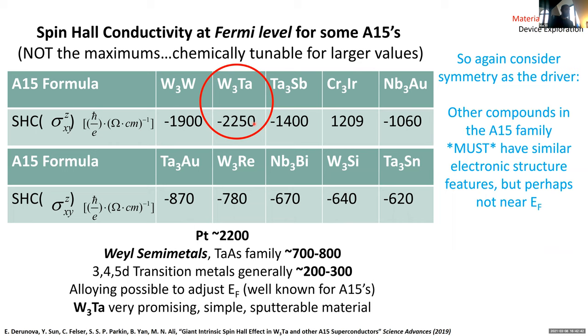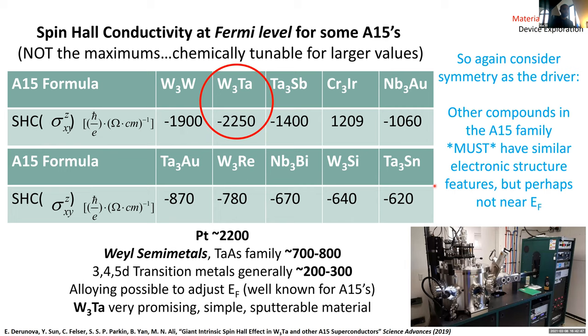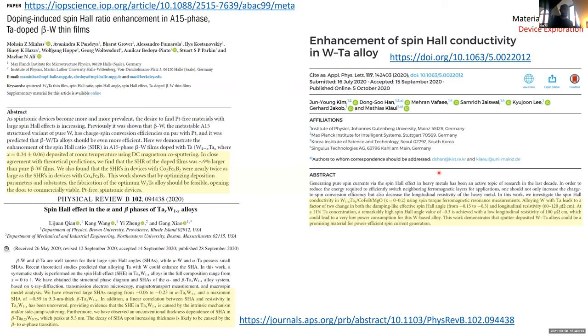So this is one of my other babies, my main piece of equipment. This is my sputtering machine that I have here in Halle. And so we, as well as several other groups around the world, took a crack at this. We said, oh, well, we should be able to make that. So we did. And we put a paper up, I don't know, last year, and happily a couple other groups, Zhao over in China and Klawi in Mainz, took a crack at the same idea based off of that Science Advances paper. And all found that, yeah, alloying with tantalum did pretty much what we expected. It increased the spin Hall conductivity roughly by the percentage we hoped. And a tangential benefit, it lowered the overall resistance of the alloy. So the tantalum doped version is lower resistance than just the tungsten version, which means it allows for even lower power. So that was great.